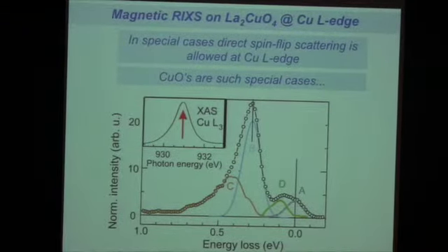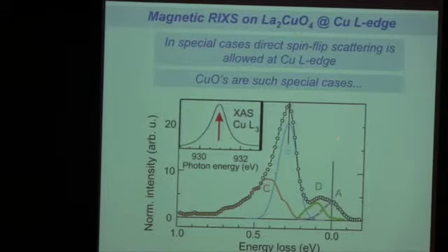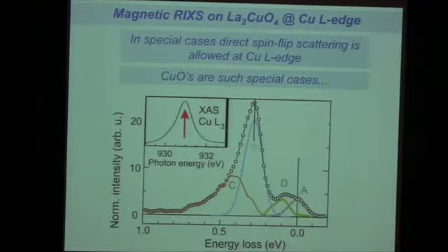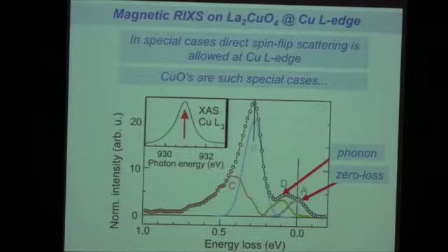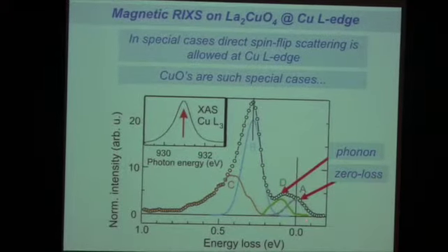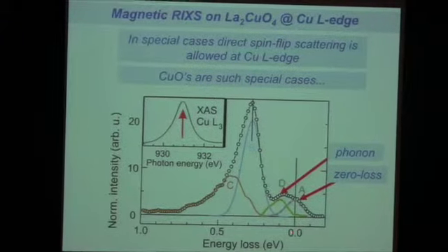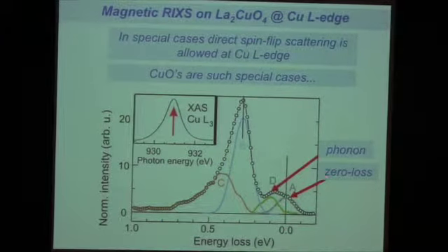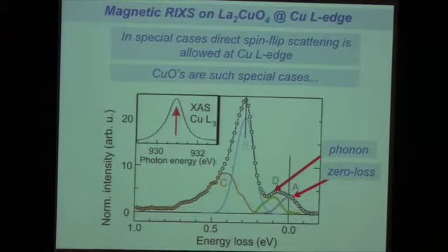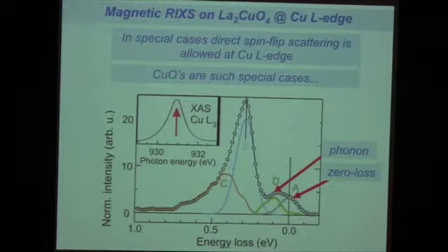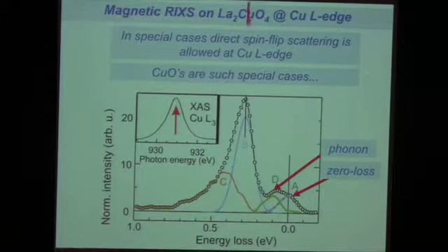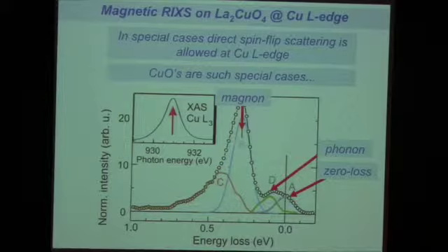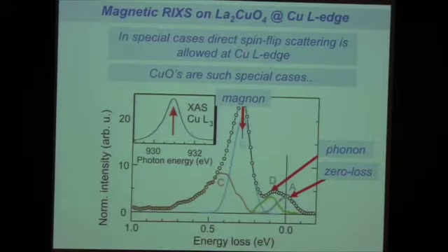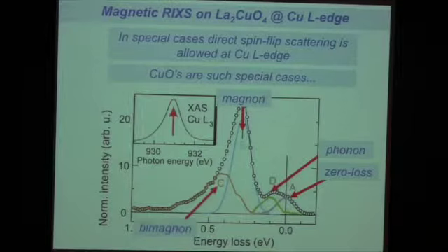Now, this is the first experiment on La2CuO4 by Braicovich and Ghiringhelli, the Italian team that really was leading, and still is leading in this field. So here, at 0, I get photons that have lost 0 energy. That's my zero loss. I'm not interested in that. These are elastically scattered photons. At about 100 millielectron volt, I have a phonon line. That's also fine. But now look at 300 millielectron volt, I have a huge peak, which is the magnon actually. It's the magnon of La2CuO4. And then at some higher energy, I have multi-magnon excitations as well.